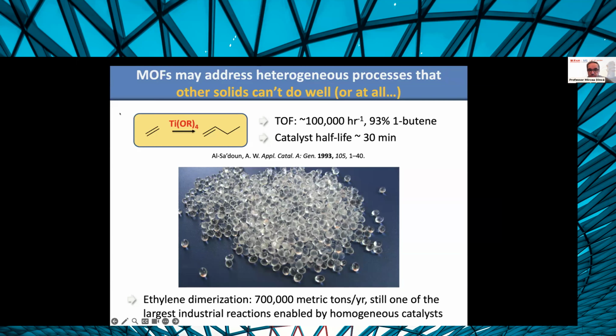One of them is the production of 1-butene from ethylene. This is a huge industrial process done on almost 1 million metric tons per year. And you would think that the industrial catalyst, which has a turnover frequency of 100,000 per hour, pretty selective for 93% butene, has only half-hour half-life. That's not the problem. What the industry cares about is that 7% of this high-purity ethylene used is actually going into unproductive process, which is polymerization rather than dimerization.